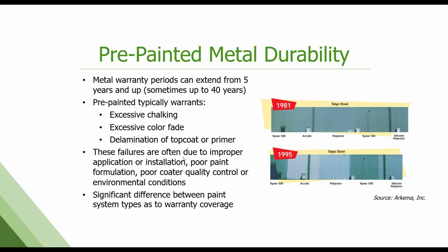So we talked about the different paint systems. You do see a lot of difference between the warranties, and I've got an example here of that. This is the same color initially. They did a Kynar 500, an acrylic, a polyester, and a silicone polyester system, all in the same color. Actually installed this on a steel company in Japan, and then checked it a few years later. And you can see that the Kynar, the PVDF system, is looking the same as it did when it was installed. The SMP is starting to fade a little bit, but not so bad. But the acrylic and the polyester are really degrading over time. Next slide.